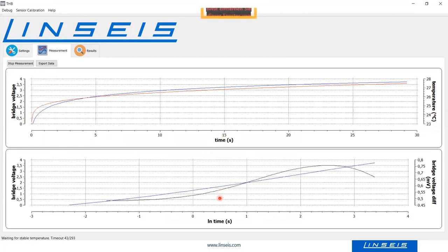And here on the bottom chart, the time axis is changed to the logarithmic scale. And then you can see the blue curve here, it's the bridge voltage, which increases linearly. And the black curve is the first derivative of the blue curve. And you can see a maximum here, which indicates the inflection point here. And at this inflection point, the thermal conductivity is calculated.